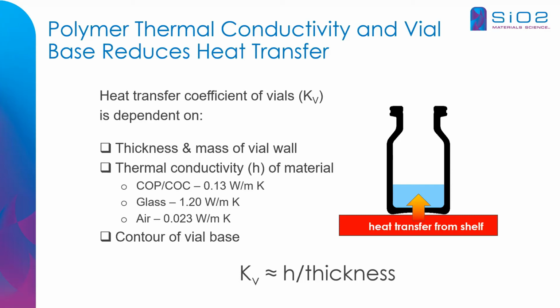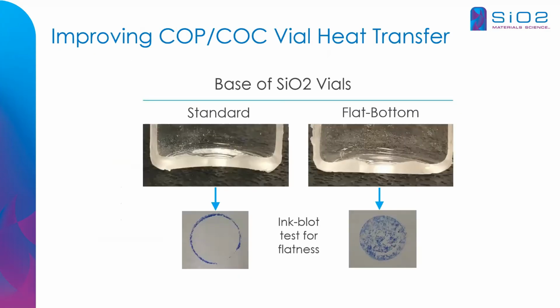So we've done a couple of things with respect to our vial to improve heat transfer. Inherent to the design is the sidewall consistency, the wall-to-wall consistency. But another thing we've done is, because we mold out of plastic, we've made flat bottom containers that increase the conductive heat transfer from the container to the shelf. In combination with the wall thickness consistency, this has really improved heat transfer overall.